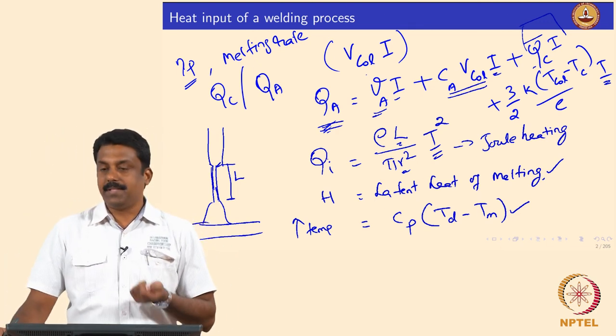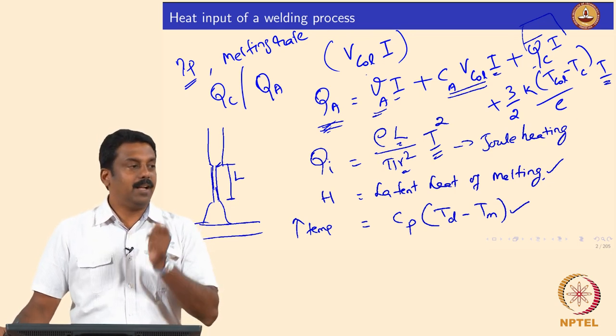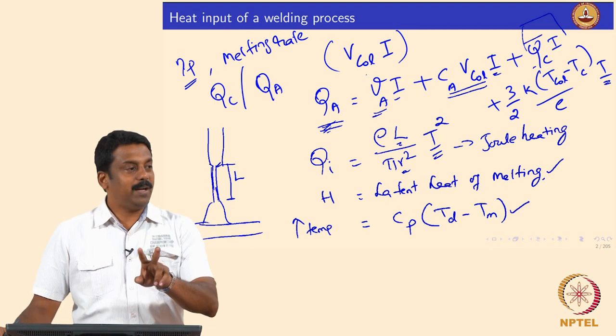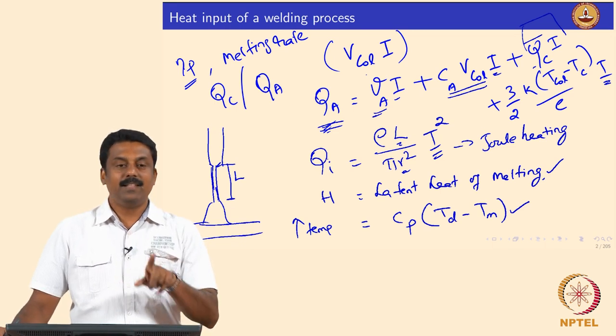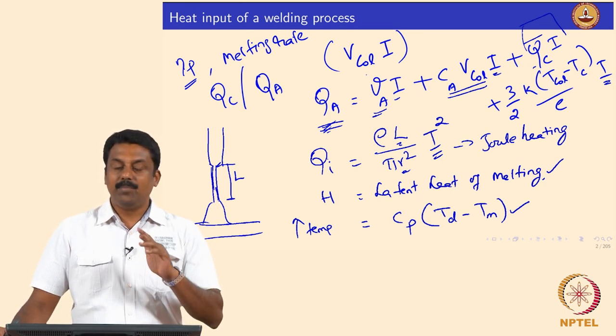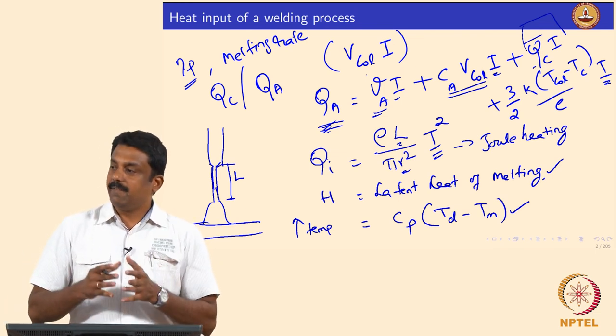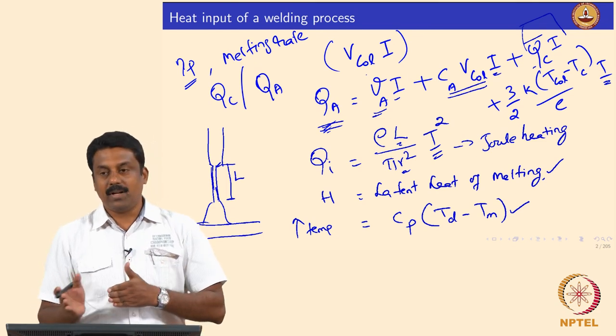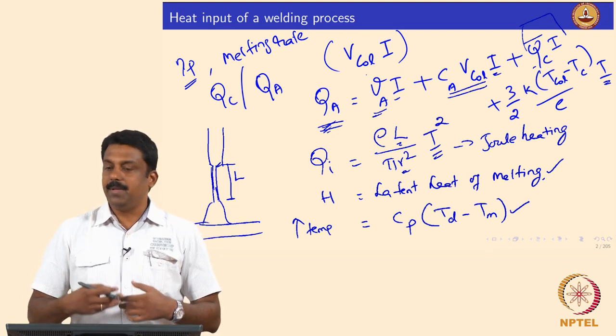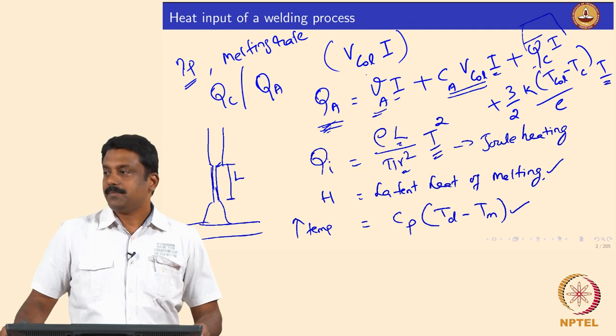For example, suppose you have 1.2 mm diameter carbon steel and you are asked to weld using GMAW with argon shielding gas — all other things are fixed. Only two parameters can be varied: current and stick-out length, to change the melting rate. Most welding process specifications for a given diameter wire and given process are generated as a function of these two parameters — stick-out length and current — because these are the only independent parameters we can vary.